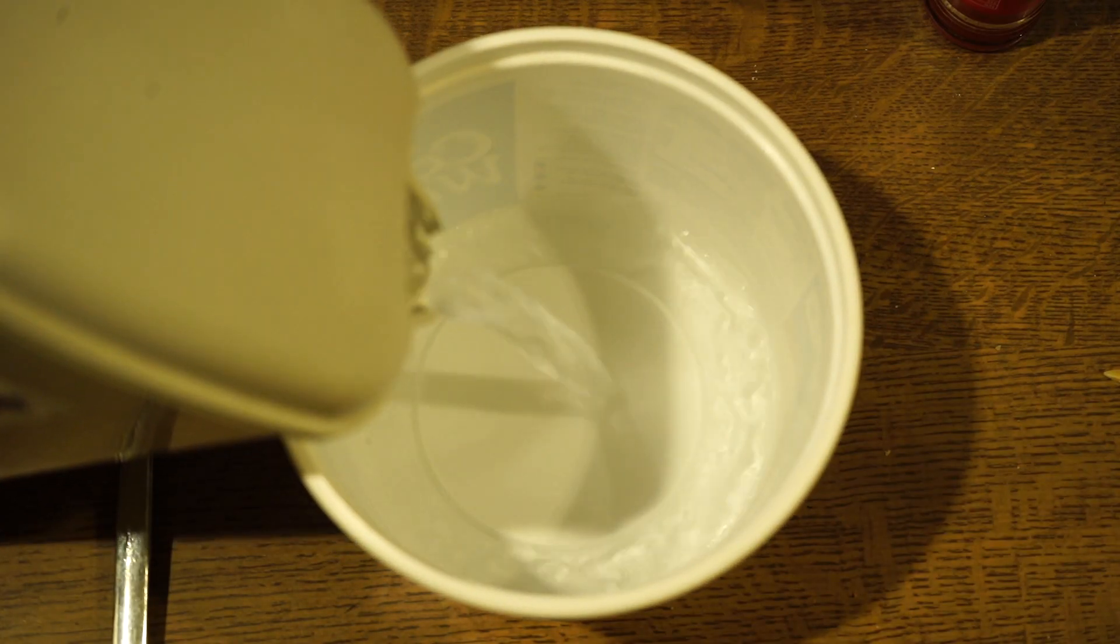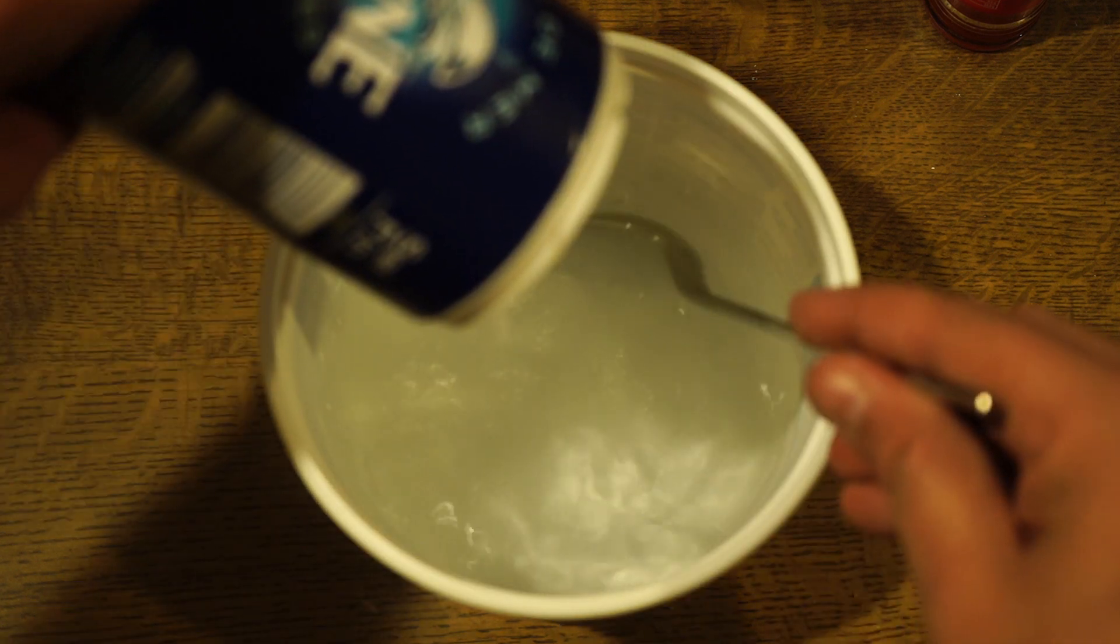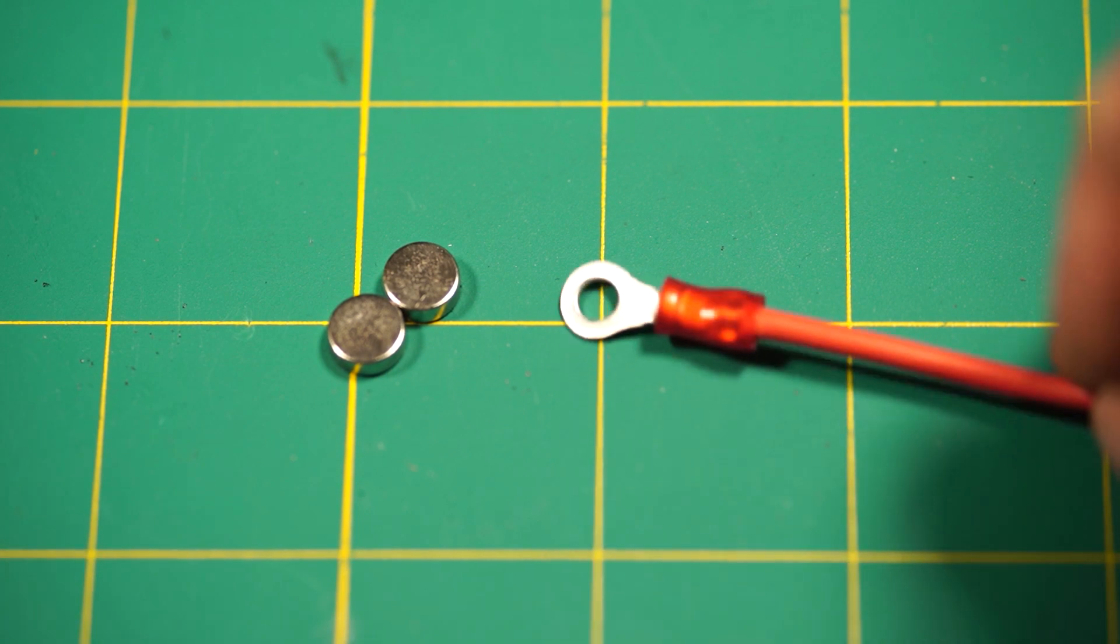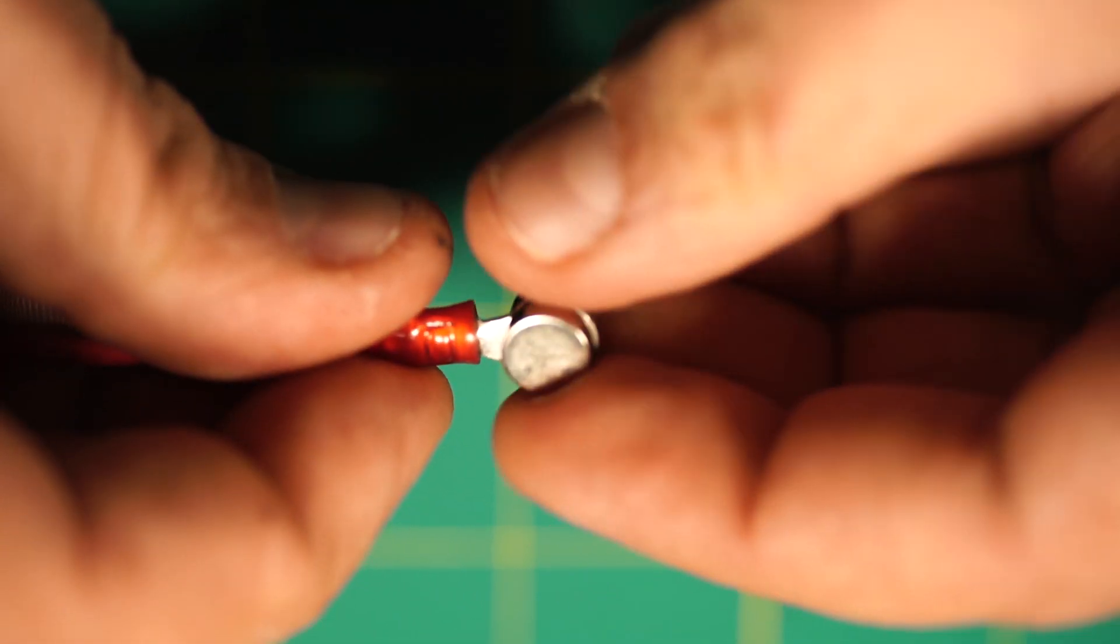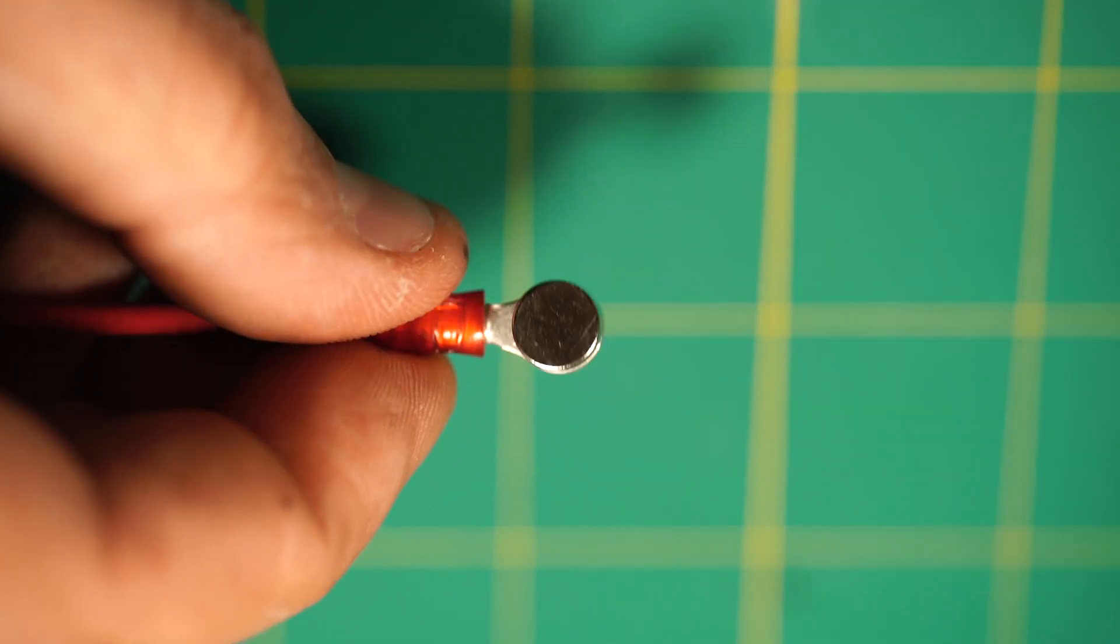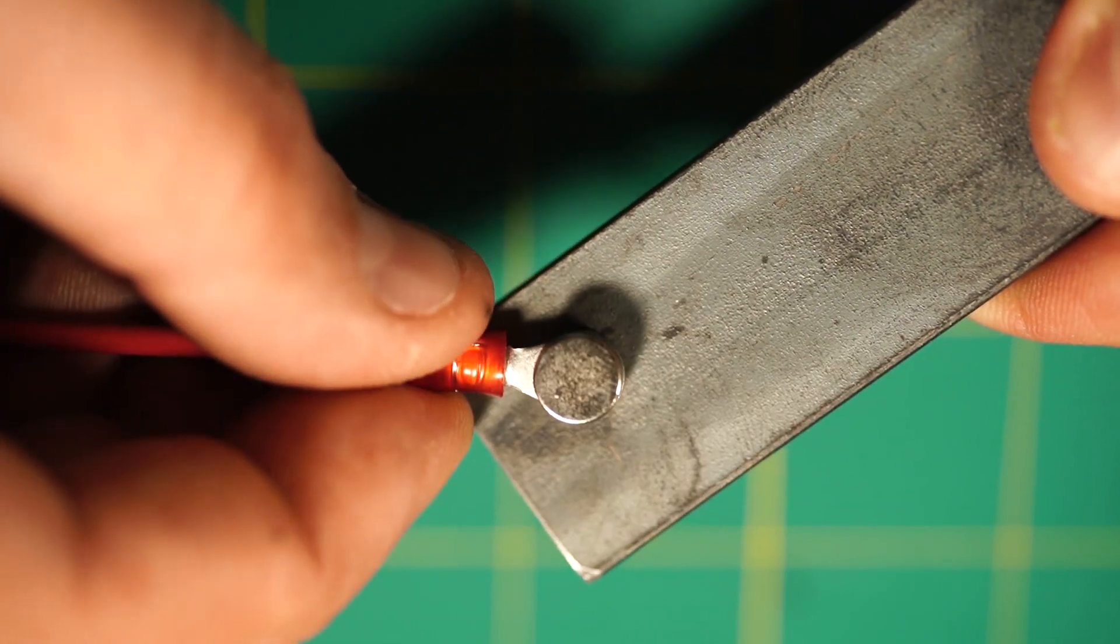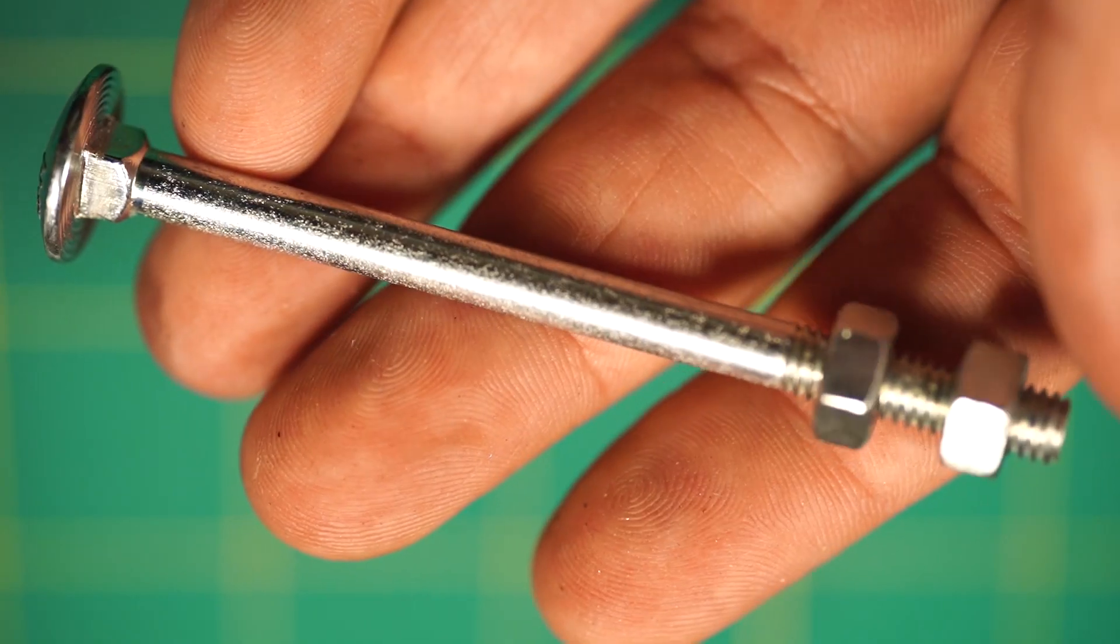Let's go over to the etching process. I am making a salt water solution by simply dumping as much salt into some hot water until it stops dissolving. As the working pieces are covered in paint, I don't want to use an alligator clip. So I came up with the idea of using two small magnets where I sandwich a ring cable shoe in between.